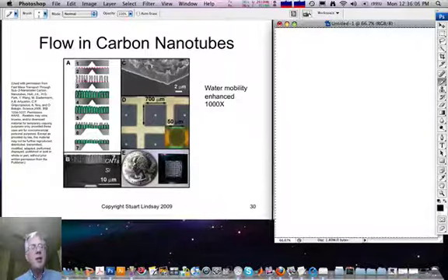It's made by growing double-walled carbon nanotubes from a silicon surface from small catalyst particles, so they stand up vertically, filling in the carbon nanotube field with silicon nitride, that's the green on this slide, opening an aperture in the back of the silicon support, etching away the silicon nitride, and then using an oxygen plasma etch to open the carbon nanotubes. One now has a freestanding membrane through which fluid or gases can be driven by the application of pressure. Here is an electron micrograph of that membrane.